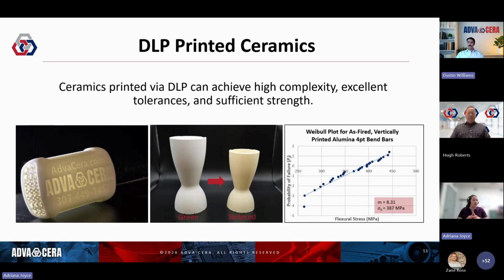Printing ceramics in general, we can achieve fantastic parts, highly complex with excellent tolerances and sufficient strength for a wide variety of applications. Either of these printers work for a variety of parts, although we pick and choose which works best depending on the part itself. We can lightweight parts with internal lattices, create complex internal channels for cooling application, and vary that strength and porosity as the application requires. As you can see in the middle image, the shrinkage during thermal processing is pretty significant. It's also anisotropic, ranging from 19 to 44%, depending on the exact material, both the resin system and the ceramic that we're working with.